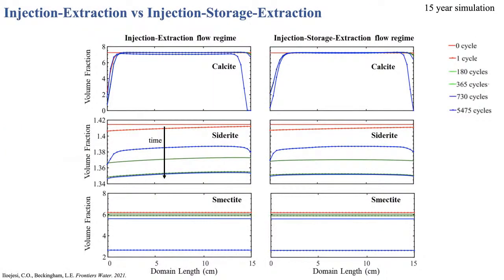Now, if we look at those different flow regimes, considering injection extraction versus a system that operates with a storage period, so injection, storage, extraction. Again, the same domain, but now we're looking at a 15-year time period. The initial mineral volume fractions are the solid red line, and then time moves downward if you're looking at the siderite plot. As before, we have dissolution of calcite closest to the injection well or close to that CO2 plume. But then we also have some dissolution further away where you're mixing with the fresh brine. We see siderite and smectite dissolution throughout the domain.